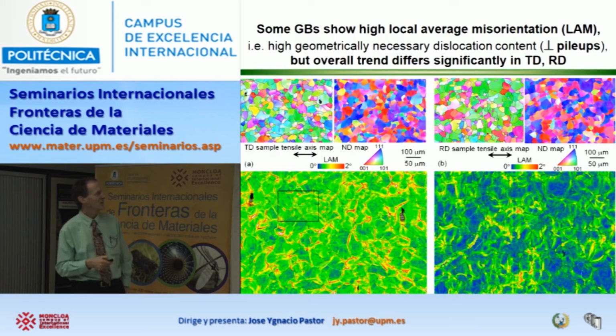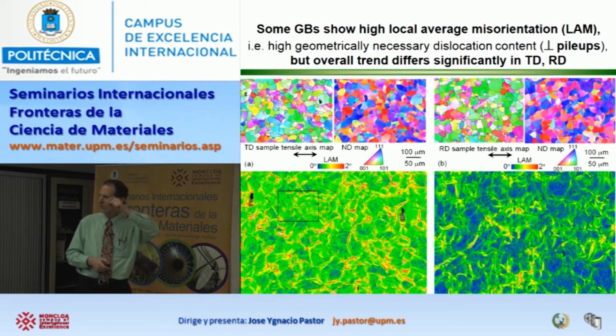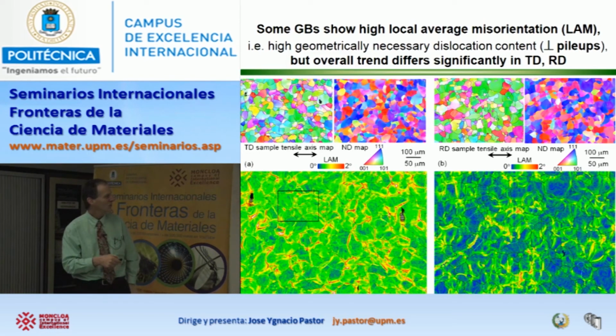If I look at a parameter called local average misorientation, abbreviated LAM, it gives me a measure of the local deviations in how the crystal is in a local neighborhood. So I choose a point, say, in the middle of a grain right there. It's sort of greenish right there, which means if I take that point and ask what my neighbors look like, how much is my neighboring pixel of material different from my orientation? If there is some bending in the crystal or twisting, then it will not be dark blue. It'll be sort of greenish or yellow.